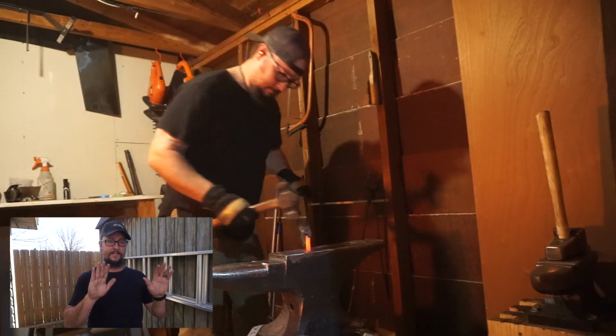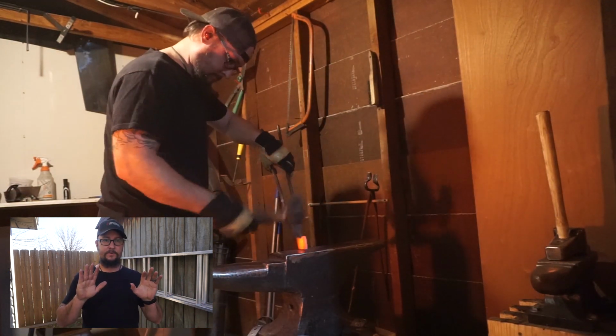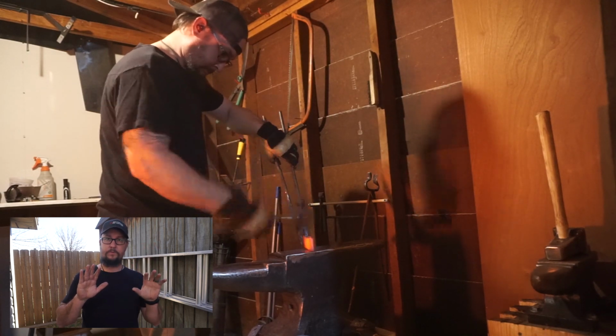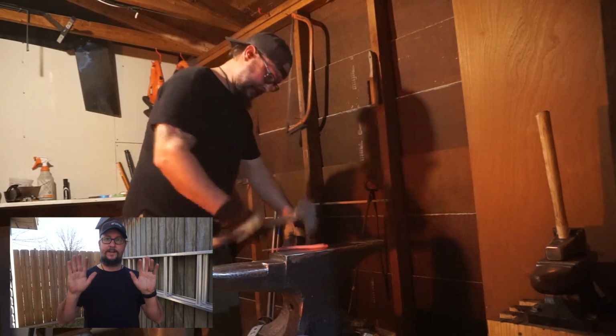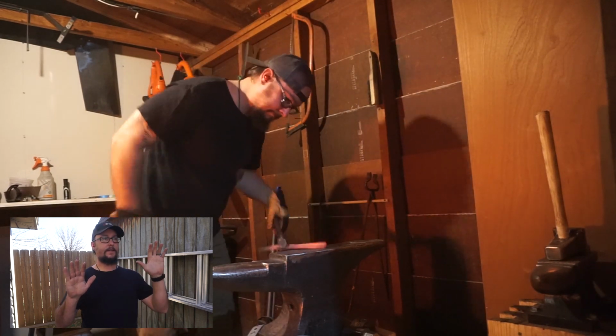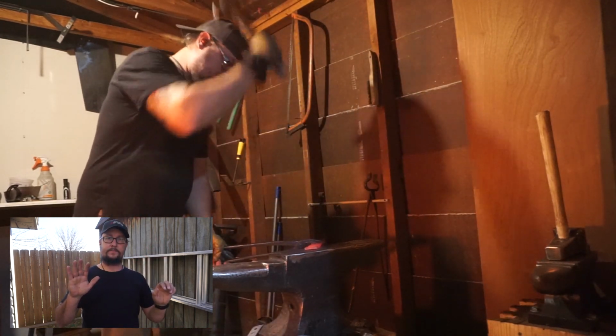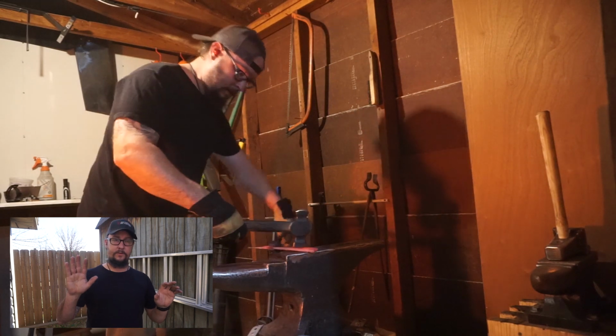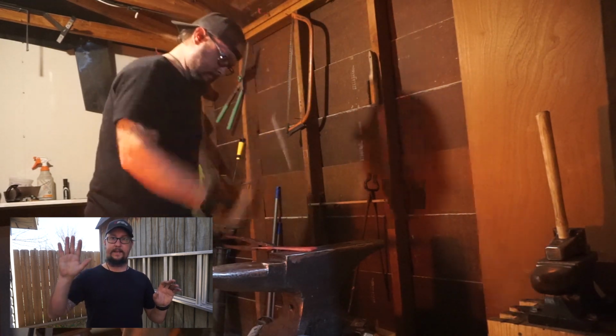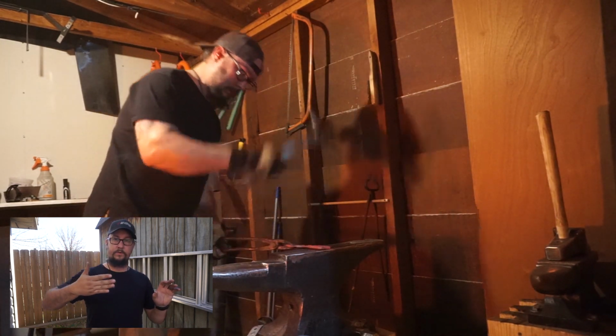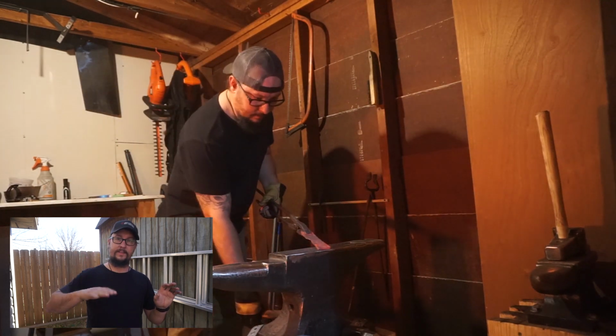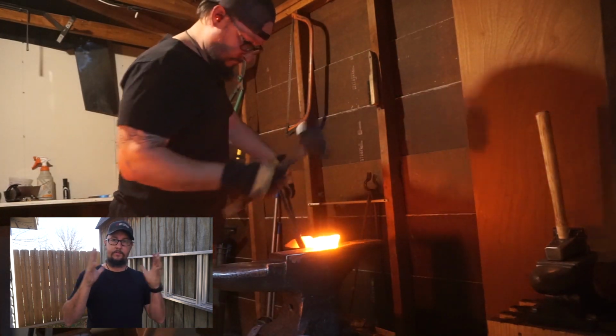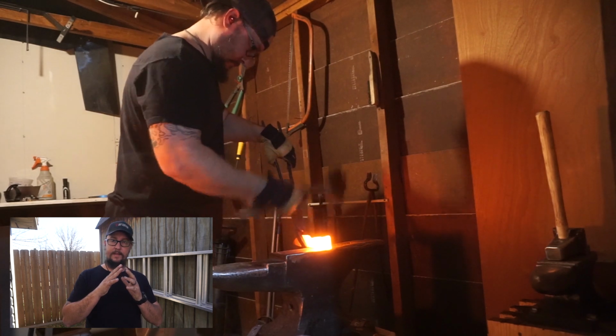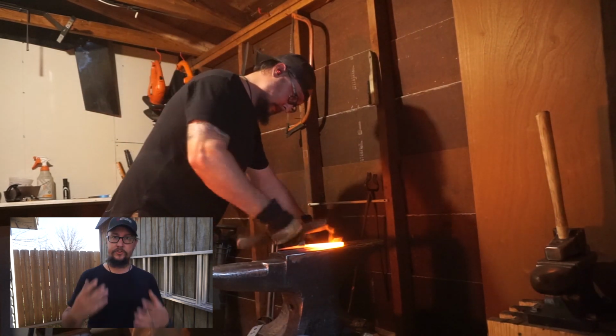So even though the processes are pretty similar, because you heat it up and let it cool, they are different processes. Annealing, you heat it up, you let it cool as slow as possible. Normalizing, you go through different cycles of heating up and then medium cool, heat up, medium cool, heat up, medium cool, refine that grain structure, and then that leads us into heat treating.